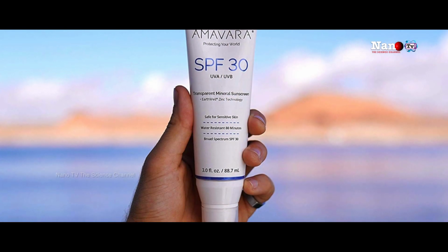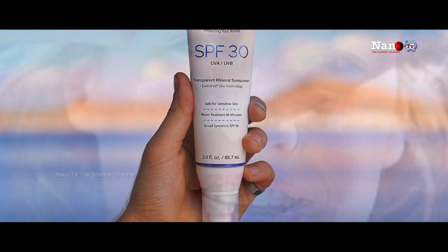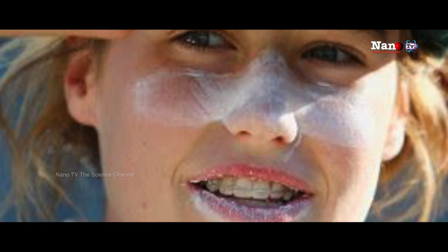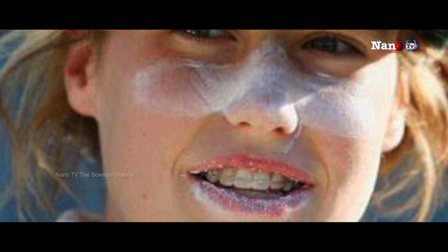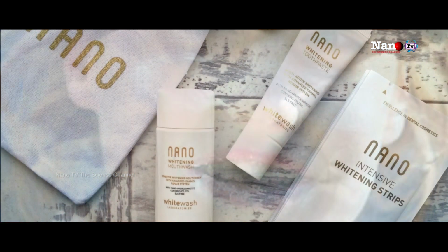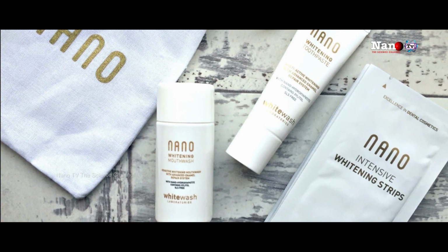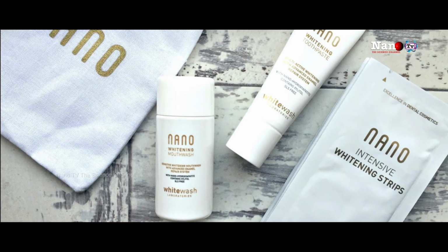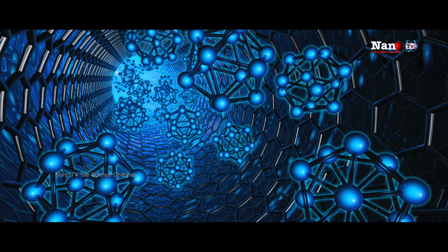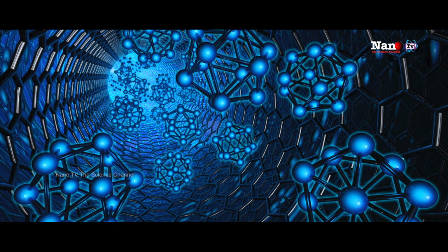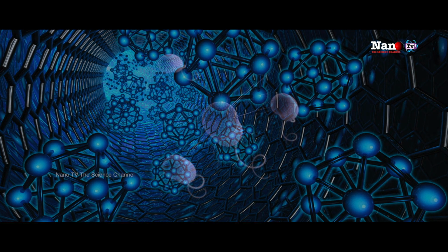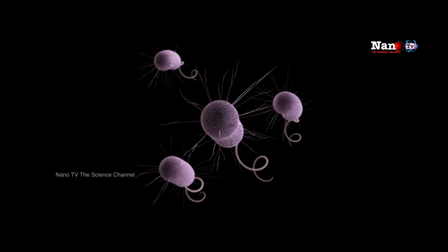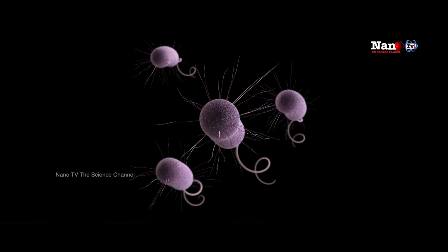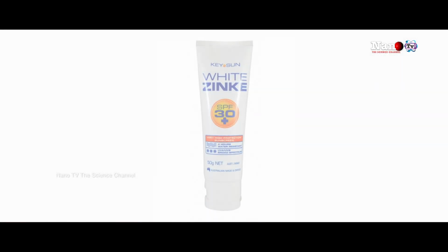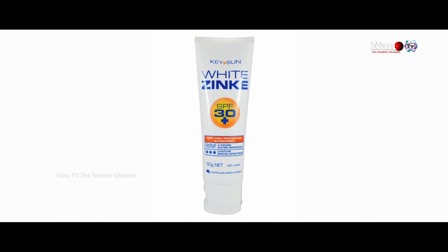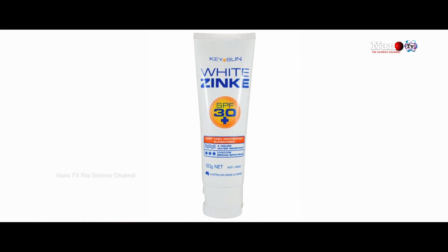That's why when sports people use sunscreen lotion, it looks white, and it is very difficult to hide when you apply it everywhere on the body. But if one wants to use a transparent sunscreen lotion with the same zinc oxide, you reduce the size to nano, maybe 10, 20 or 30 nanometers, and this nanoscale is far less than the visible light spectrum, that is 400 to 800 nanometer. So the scattering losses will come down, and then it will be quite transparent. Now the new technology of cosmetics is coming with nanoparticle-embedded sunscreen lotions for transparent sunscreen.